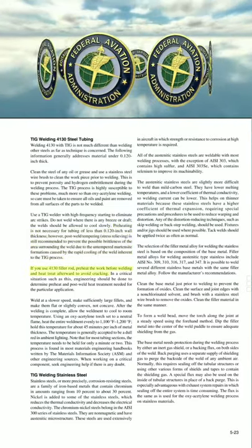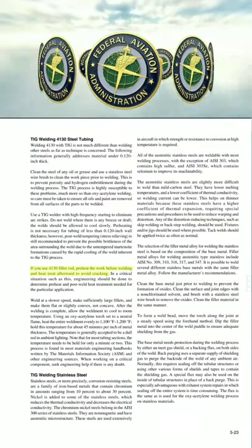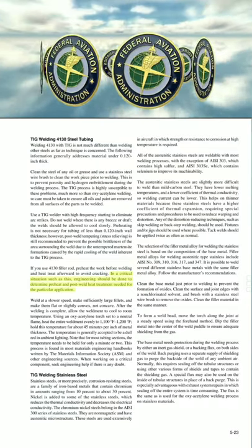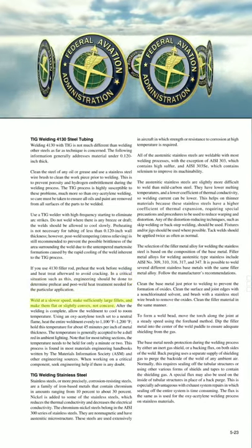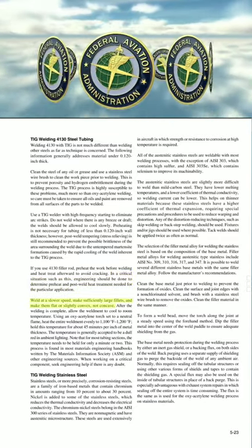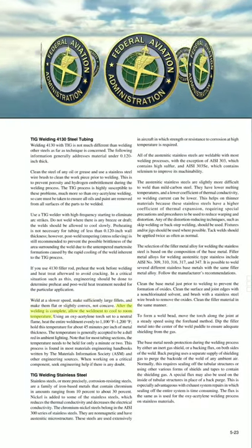If you use 4130 filler rod, preheat the work before welding and heat treat afterward to avoid cracking. In a critical situation such as this, engineering should be done to determine preheat and post-weld heat treatment needed for the particular application. Weld at a slower speed, make sufficiently large fillets, and make them flat or slightly convex, not concave. After the welding is complete, allow the weldment to cool to room temperature.